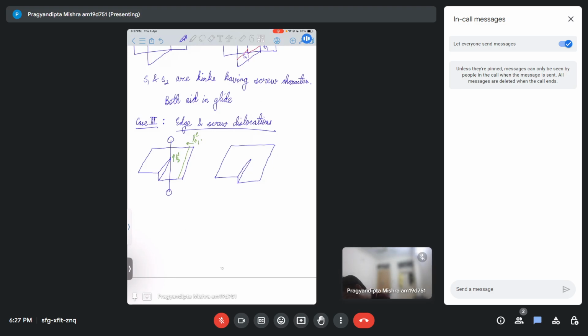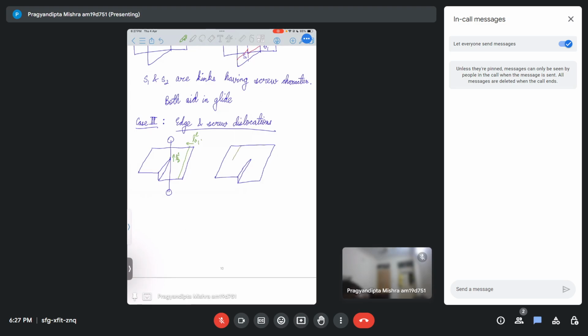So now the edge dislocation also gets broken, right? So this is my edge. It gets broken like this, in this direction, and then continues on. So this is my S1 here. This is my edge dislocation, having Burgers vector B1 in this direction. So this results in the formation of a jog here, which has an edge character, right? But what happens to the screw, which has the B2 Burgers vector?